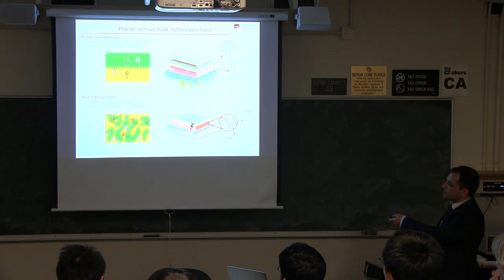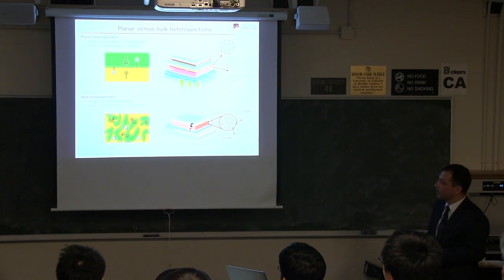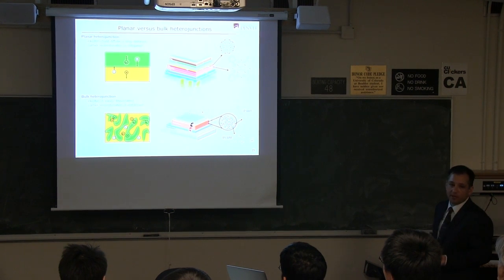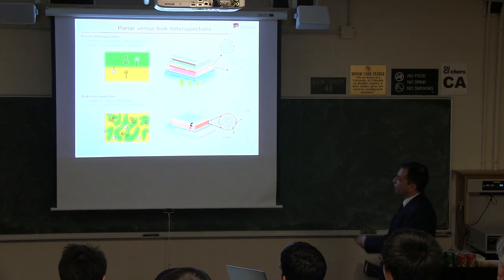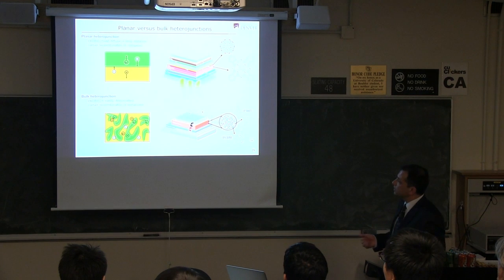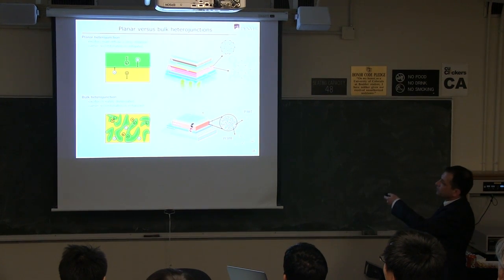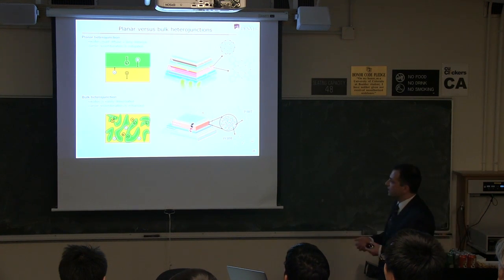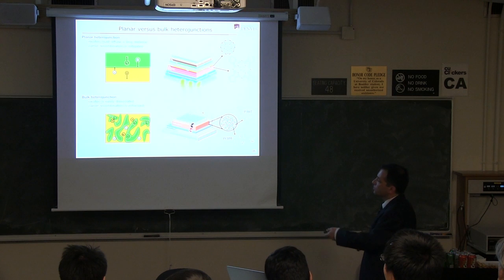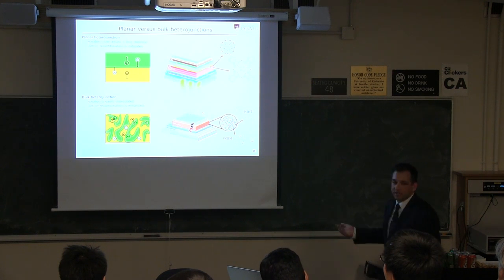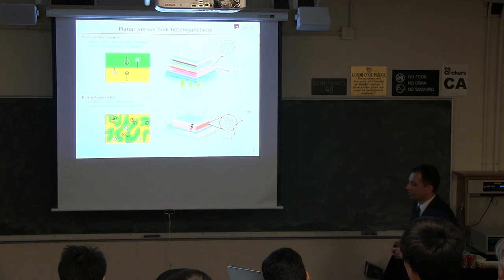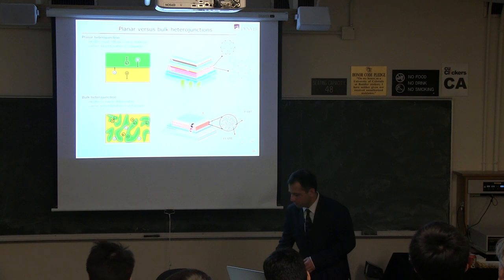Once you have the charges, the pathways for actually getting out of the device can be quite tortured, and carrier recombination can be a problem. So both approaches are tried, both work. So the Heliatek 12% device looks something like this with the multi-layer stack of these planar heterojunctions. But Mitsubishi and other companies, and universities, are using this approach to get 10 and 11%. So either strategy can work, but you should know that there's two different ways to do this.